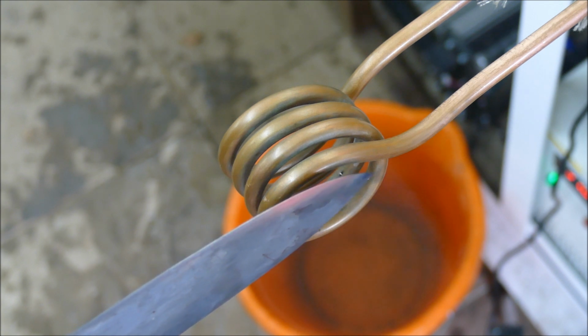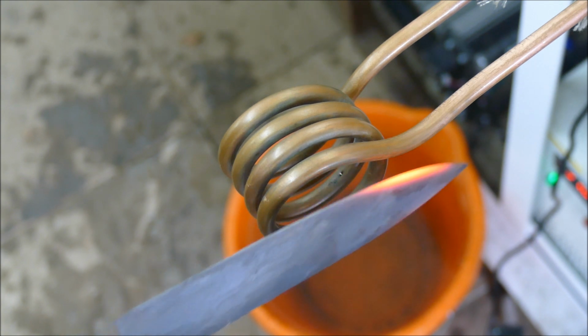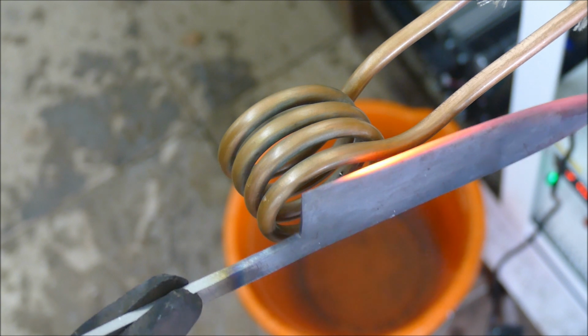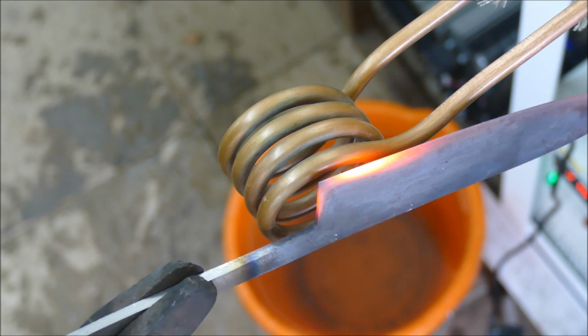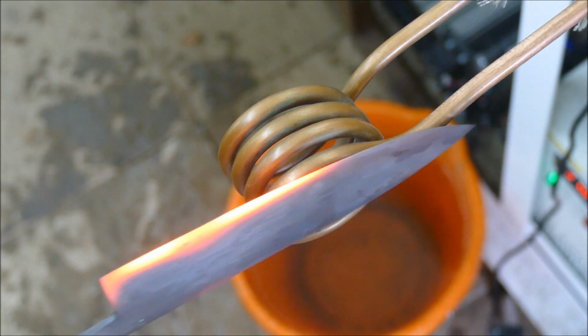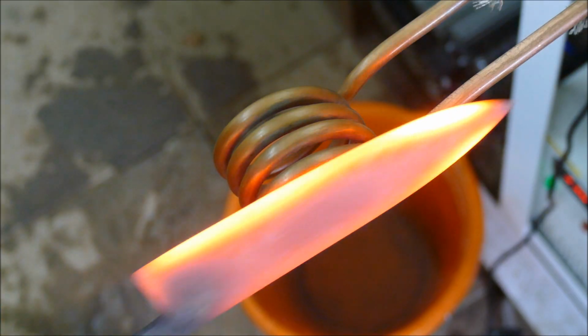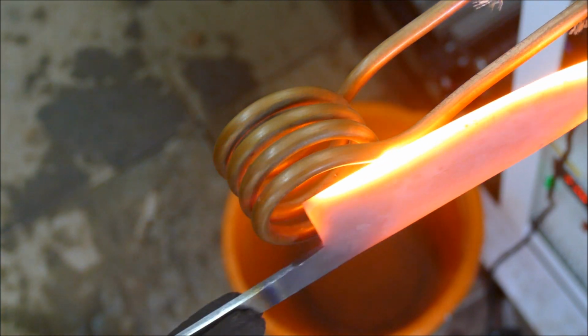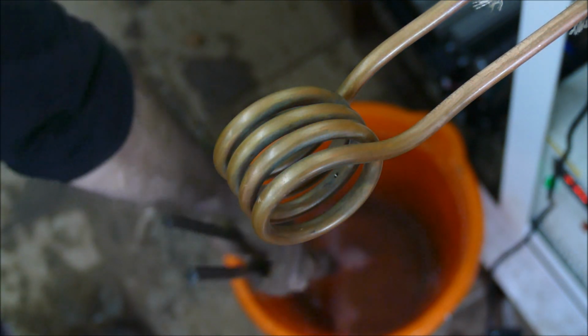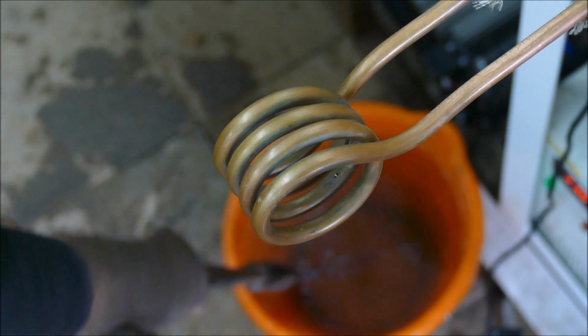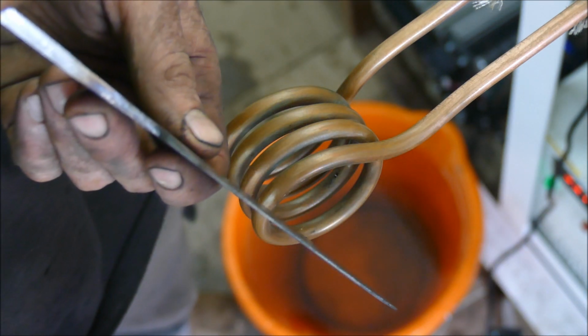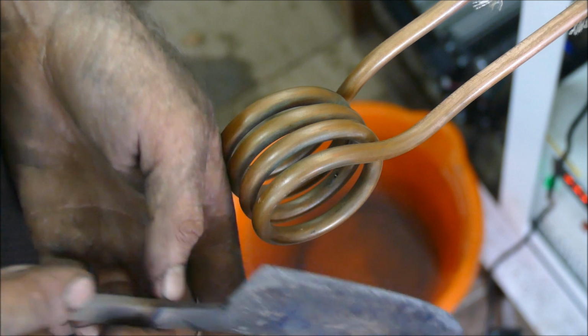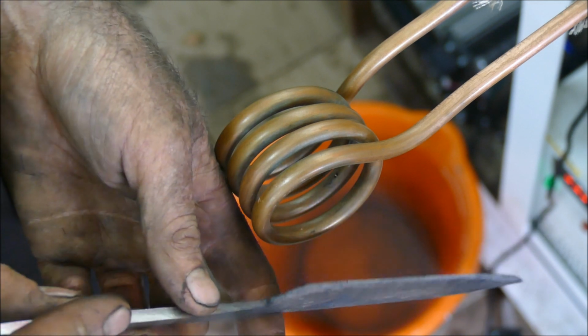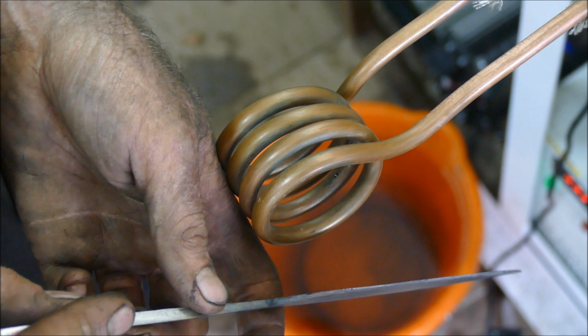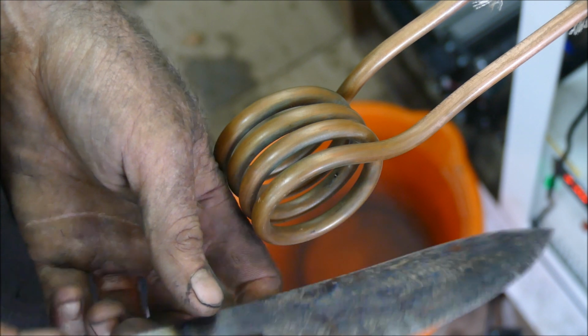So the benefit that's happening here is that only the core of the steel is getting heat treated, and that cladding is actually remaining quite malleable. Theoretically, this means I can be quite brutal when it comes to the heat treatment and get that steel extra hard, and that laminate layer is actually improving its properties, stopping it from becoming as brittle as it would be normally. I've also quenched in water, which is what they would have used traditionally. But there's also a risk of cracking and bending when you do that. But having that soft, malleable layer, I believe, is preventing that from happening.